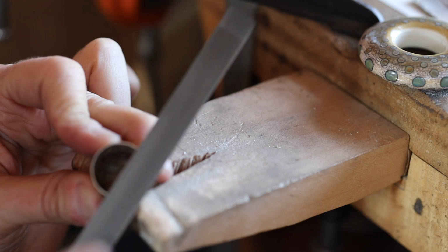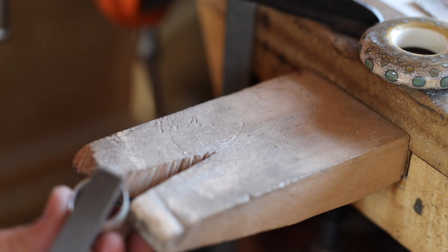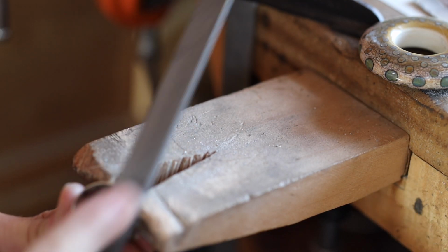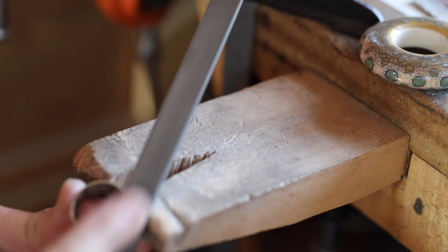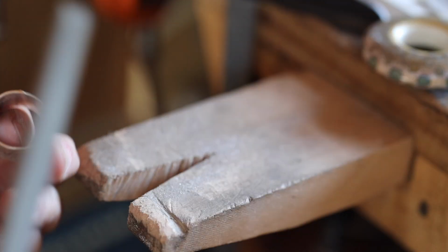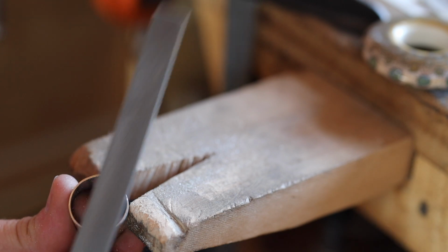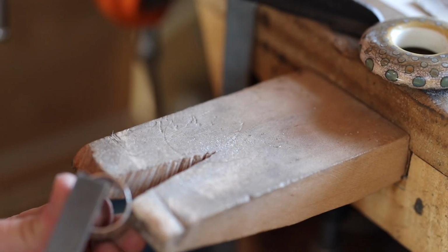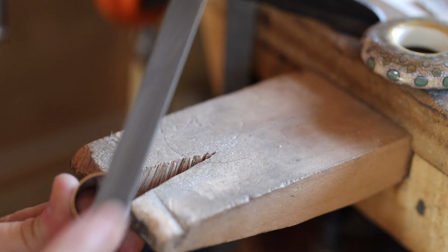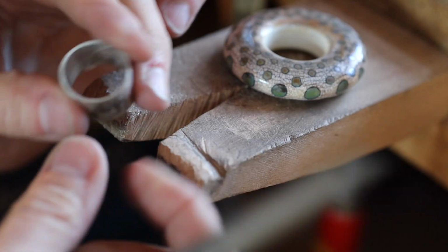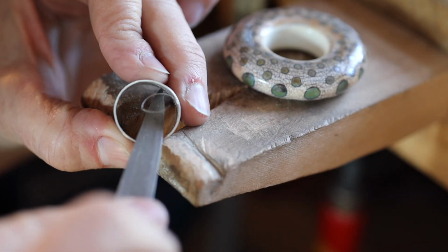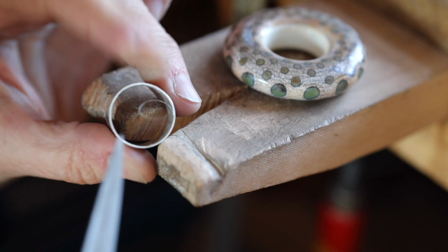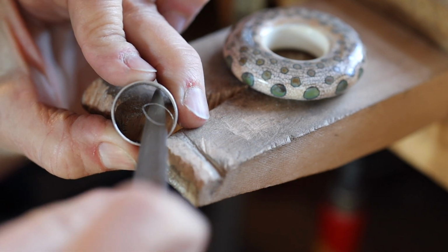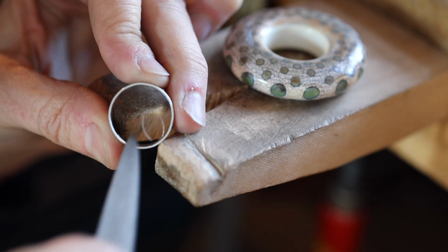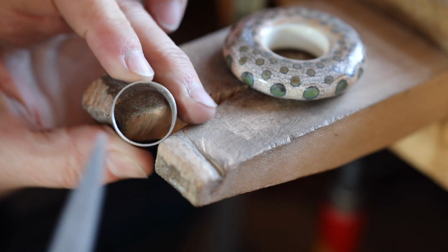It's super important to clean up the edges of the silver and not leave any little nicks or saw marks in that outside ring, as anything like a little nick or a mark can initiate a tear in the silver when you're actually creating the rivet and asking it to stretch. So this stage is really important.